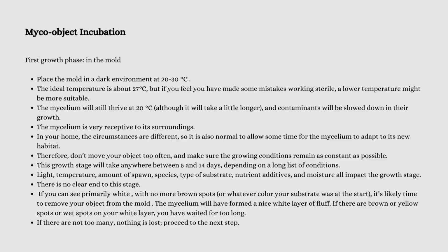One thing that I want to mention is that there are two potential growth phases when you are making your mold. First, you can have your first growth phase, and this will completely myceliate your form. However, in the second growth phase, you can take out your piece from its mold and not dehydrate it yet, but allow it to keep growing.